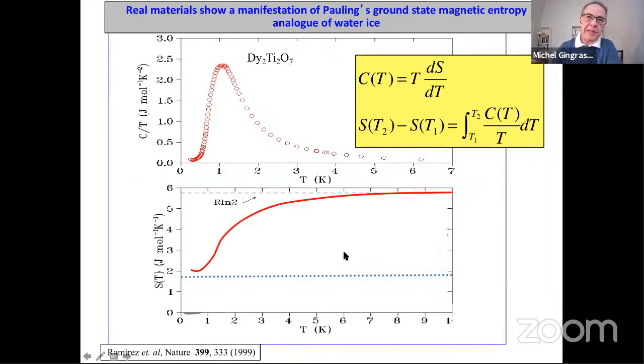And so this is what it looks like. At very large temperature, we know what the entropy should be. It should be log 2. You have two states per site. And so at very large temperature, which means for all practical purposes above 10 Kelvin, the entropy should be log 2. And that fixes the constant of integration at 10 Kelvin. And by integrating the area under this curve of C over T, one finds that the entropy goes down.